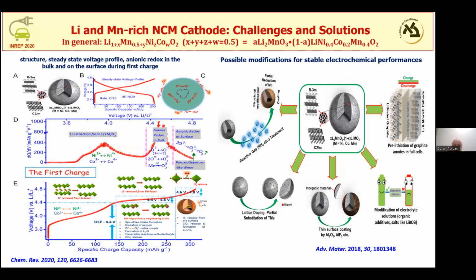Now I move to another, very interesting family: the lithium and manganese rich NCM. Here we have the same five elements, but we change the stoichiometry. We have again lithium, manganese, nickel, cobalt, oxygen. But now the stoichiometry of lithium, which was previously 1, can be 1.13 or up to 1.2. The manganese is at least 0.5, and the rest is nickel and cobalt. We leave oxygen at this stoichiometry. So we call these materials lithium and manganese rich NCM cathode materials.